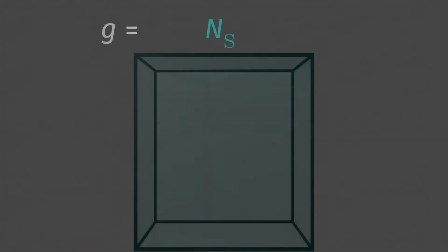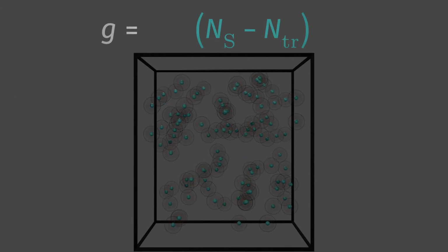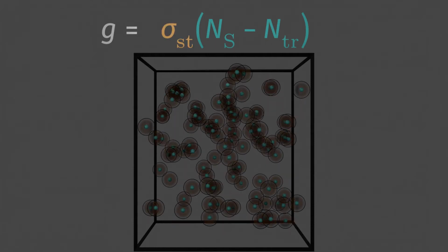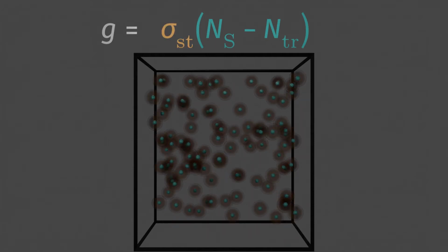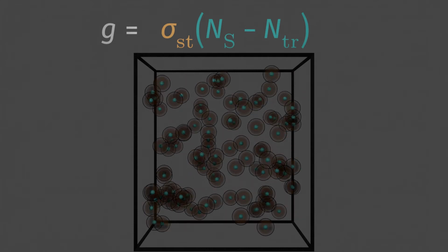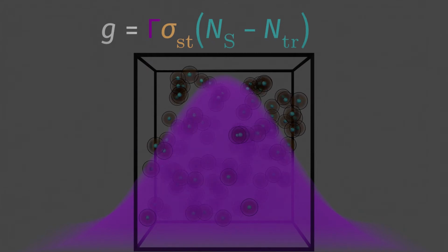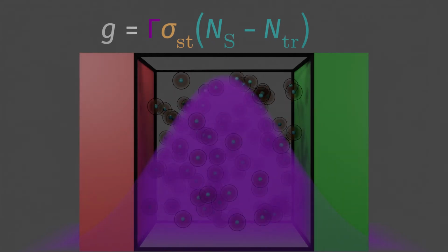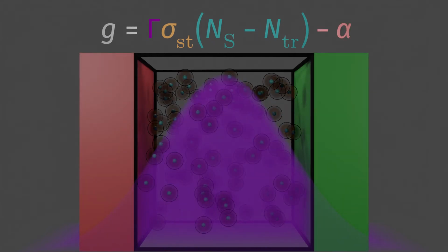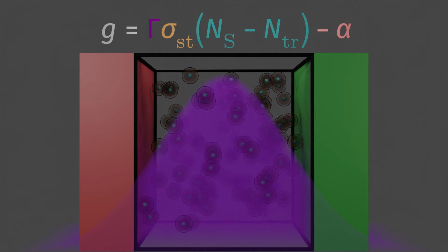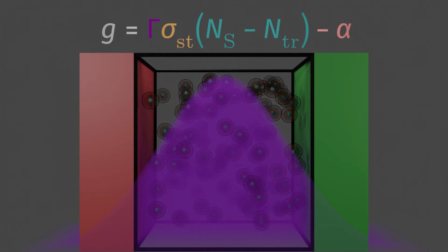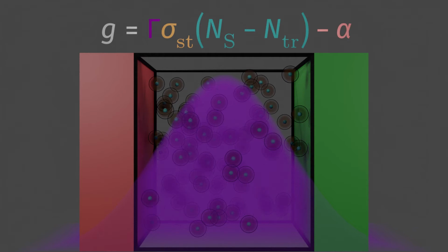Focusing on the singlets in the active area, the gain depends on a few parameters. The density of singlet states for one, or more importantly, the number above the transparency density. Second, each of the singlets have a stimulated emission cross-section to interact with the lasing mode, and not all of the mode necessarily overlaps with the active area. Some of the mode will interact with structures that will add to loss, but even if we could remove all of these losses, the nature of populating singlet states electronically will add additional loss.